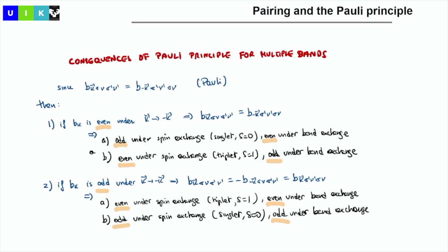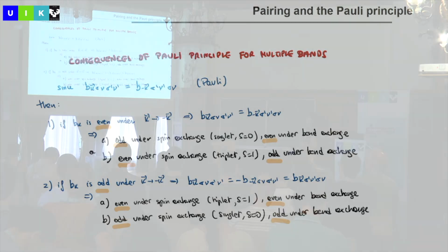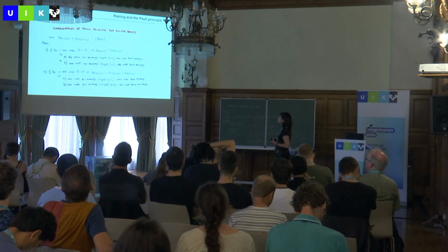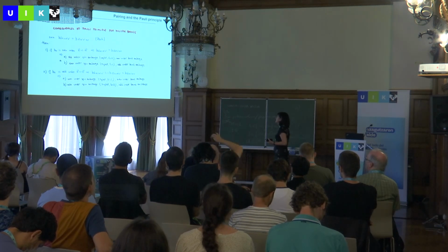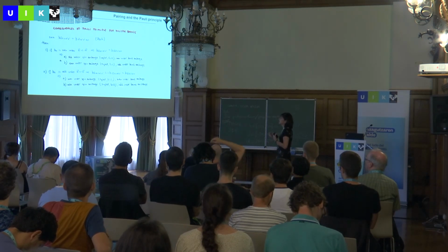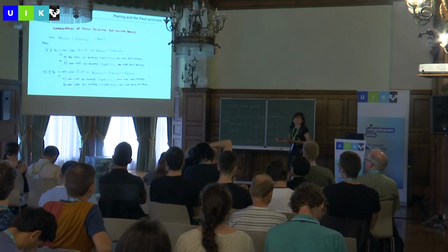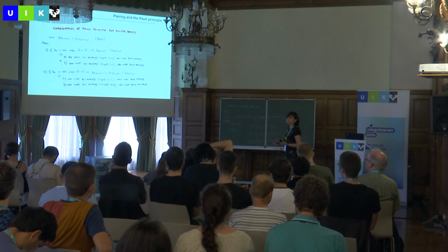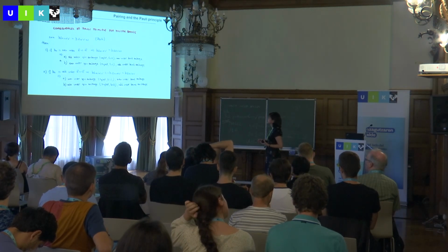then we have the possibility of a state, a Cooper pair, which is a singlet and is even under the band exchange or the orbital exchange, or is even in the spin exchange and odd in the band exchange, just to fulfill the Pauli principle. On the other hand, if it is odd under k to minus k, then imposing the Pauli principle, we can have a triplet superconductor that is even in the orbital channel, while it can be odd, so a singlet in the spin channel and odd in the band channel. So these are all the options, and depending on the system we are dealing with, one can go through all these options, which are in fact determined by the symmetries of your system.